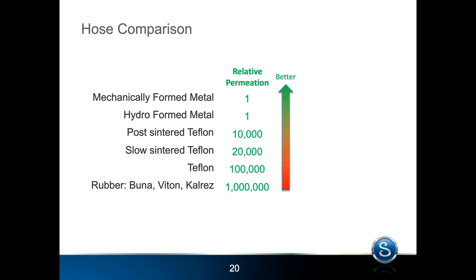So again, in general, when selecting a hose that's going into a situation where permeation is a concern, all metal is by far the best. But if you need to use a Teflon because of things like vibration, like was just mentioned, or cleanability because of the smooth bore, make sure the Teflon core has been sintered to some fashion, and post-sintered again is the best. Okay, looks like people are still with me. We're going to move on now to